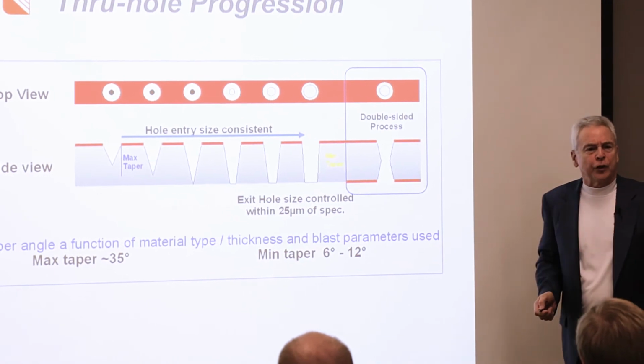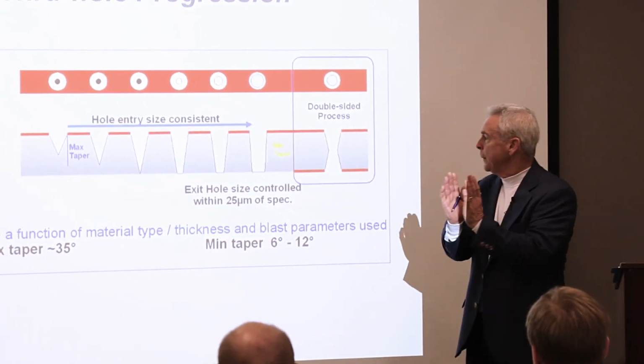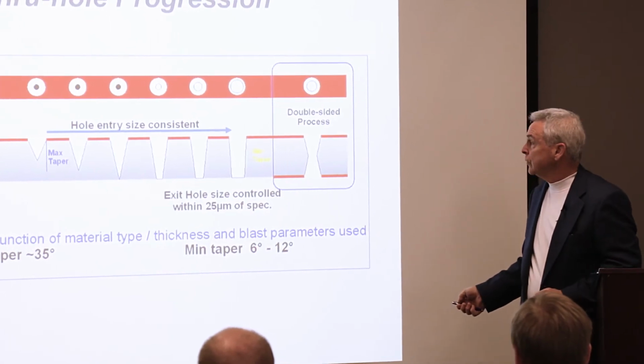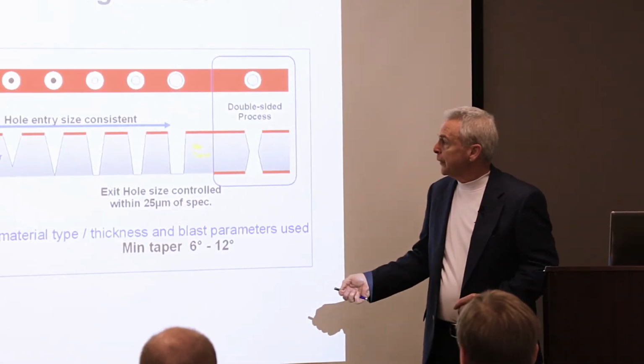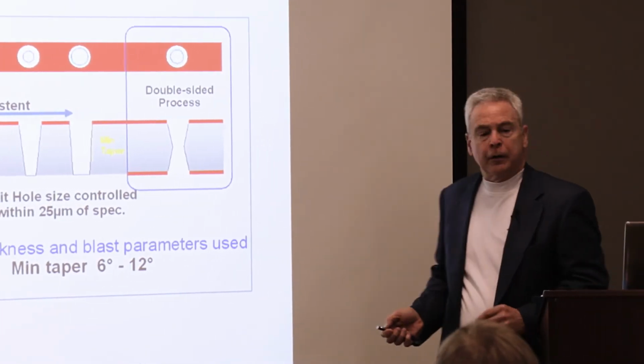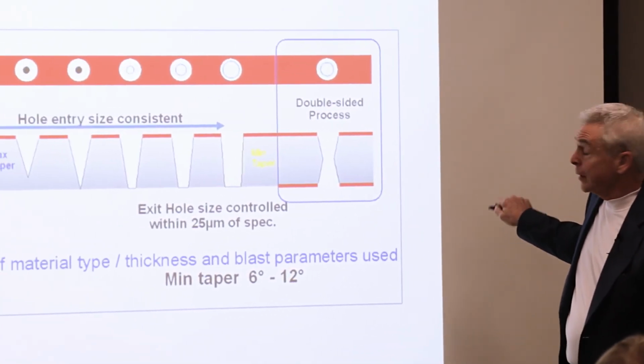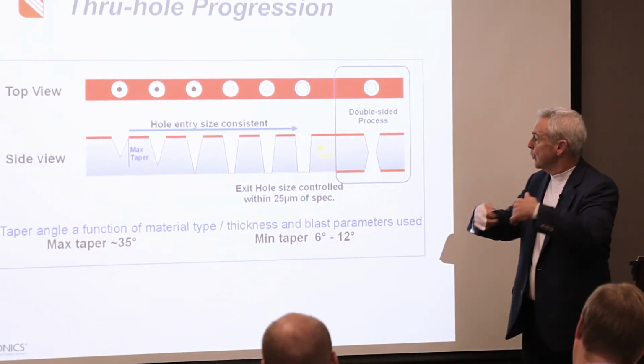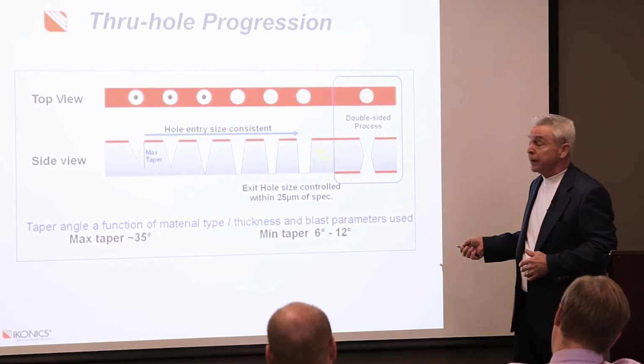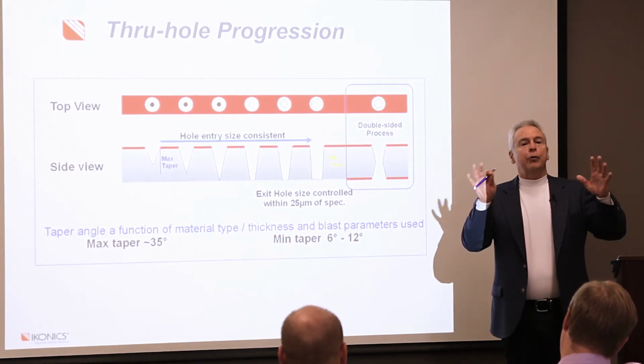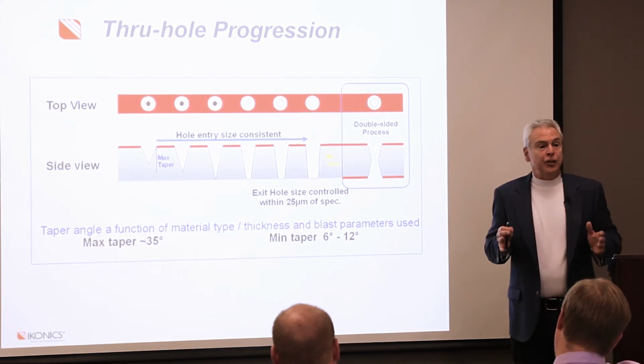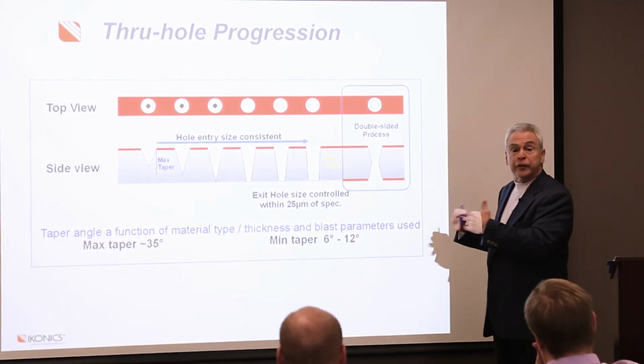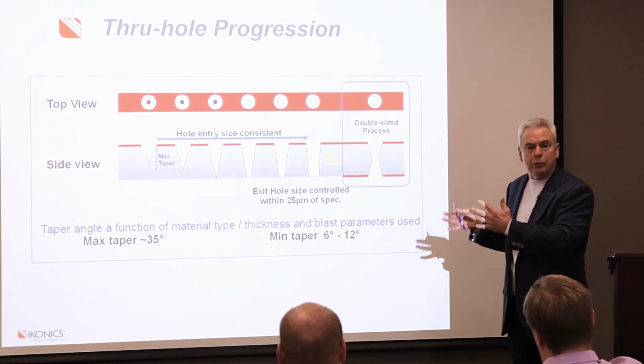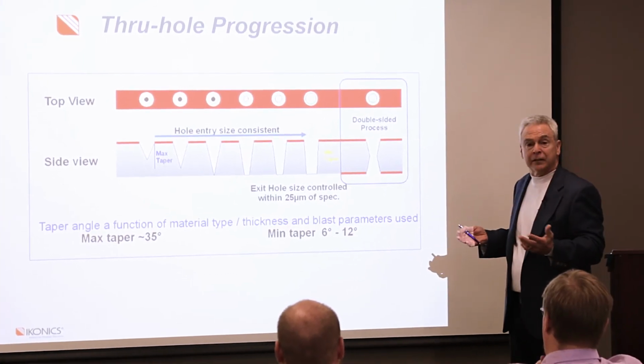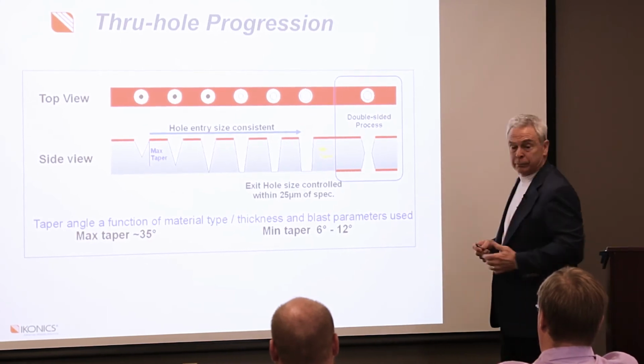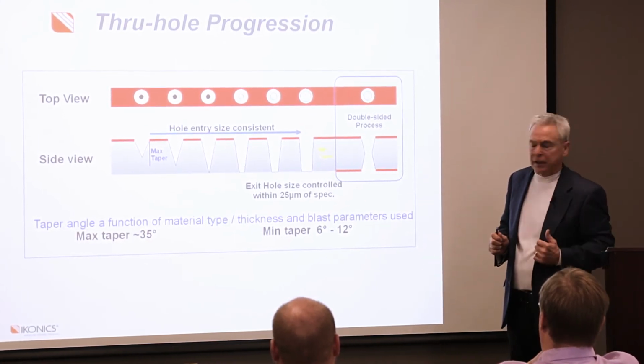Now you say, well, gee, it's not a straight hole. No, that's right. You always end up with a taper. You can get it down to about 6 degrees, minimum taper here. It starts out at about 35 degrees. And the reason for that is because as you blast from the top to the bottom, you actually lose energy as you're blasting. So you're going to end up with less energy to remove the material on that sidewall. You say, well, gee, that's going to be a problem. Well, the fact is that in some applications, that's actually an advantage, because acoustically, you can possibly tune this to create a more acoustical effect and sound deadening when that taper is the right shape for a particular application.